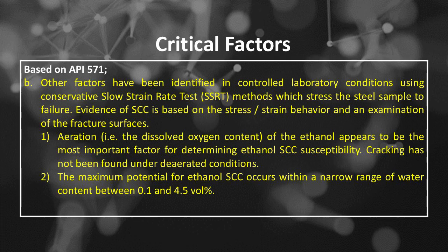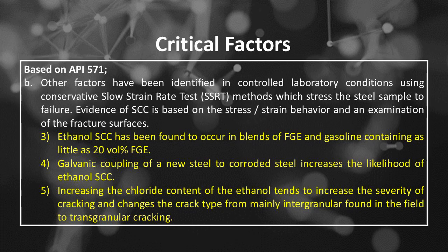Number 2, the maximum potential for ethanol SCC occurs within a narrow range of water content between 0.1 and 4.5 vol%. Number 3, ethanol SCC has been found to occur in blends of FGE and gasoline containing as little as 20 vol% FGE. Number 4, galvanic coupling of a new steel to corroded steel increases the likelihood of ethanol SCC. Number 5, increasing the chloride content of the ethanol tends to increase the severity of cracking and changes the crack type from mainly intergranular found in the field to transgranular cracking.